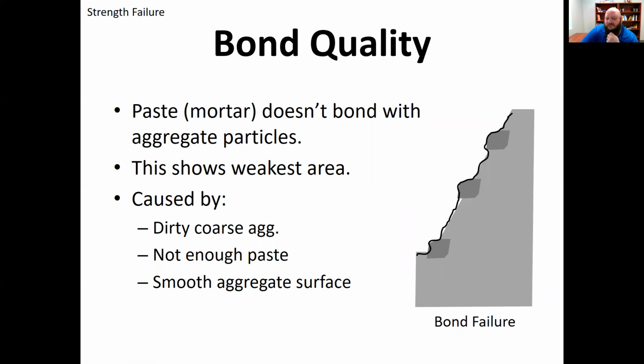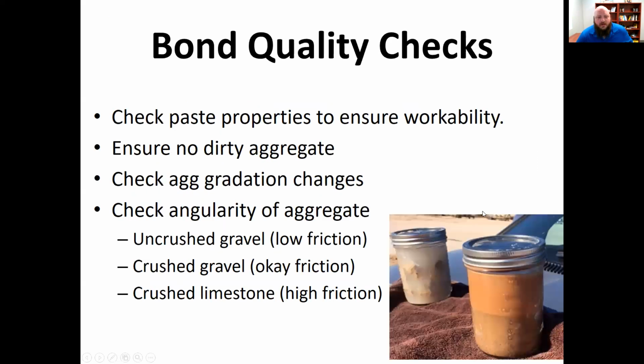In essence, the paste does not bond well with the aggregate particles. That's what's happening whenever you have aggregates that are just sticking out of the cylinders like you see here. So that's not good. Sometimes you have dirty coarse aggregate, so you need to really wash it. Sometimes it's because of the smoothness of that surface, so you really want it crushed if you can. Other times you may just not have enough paste in your mix. So kind of realize that.